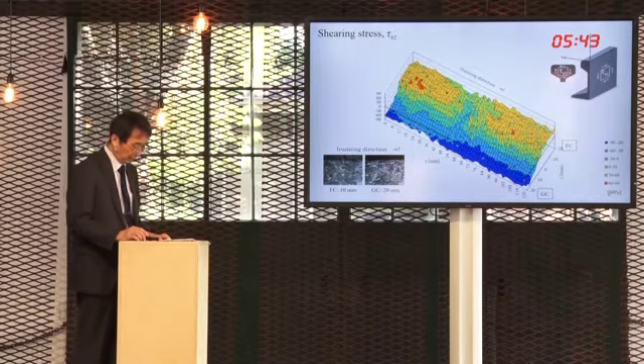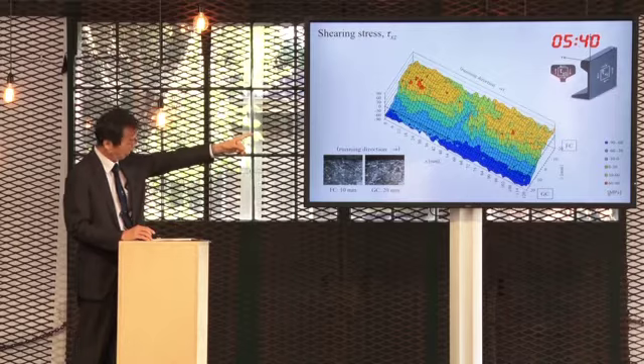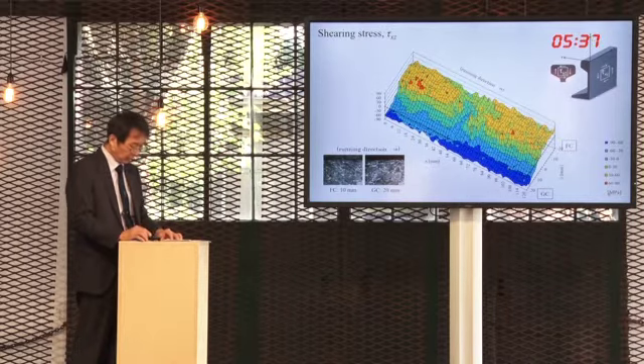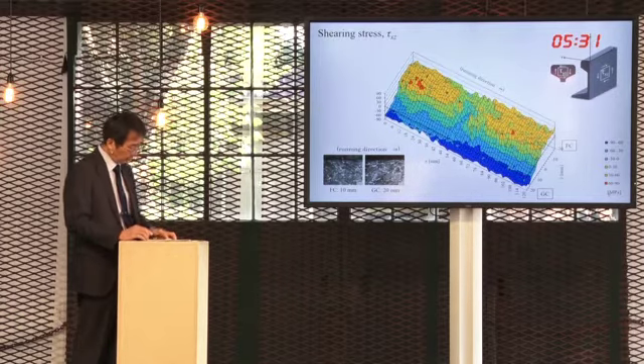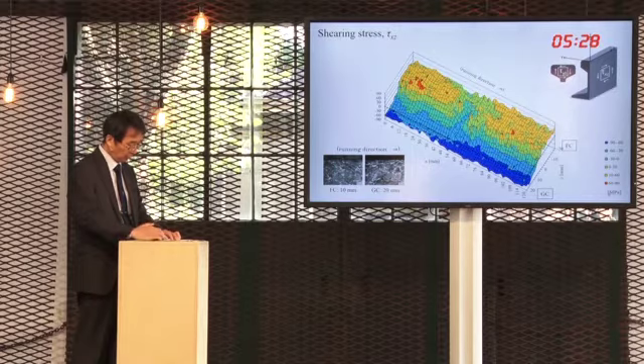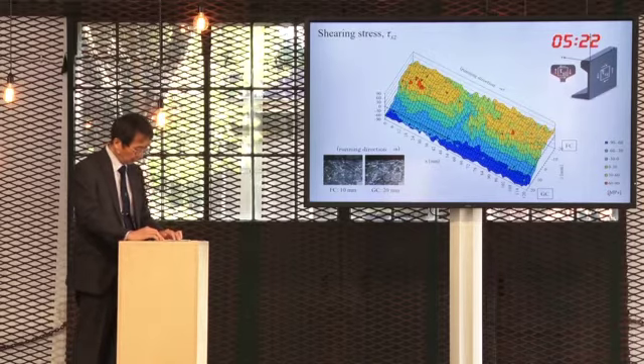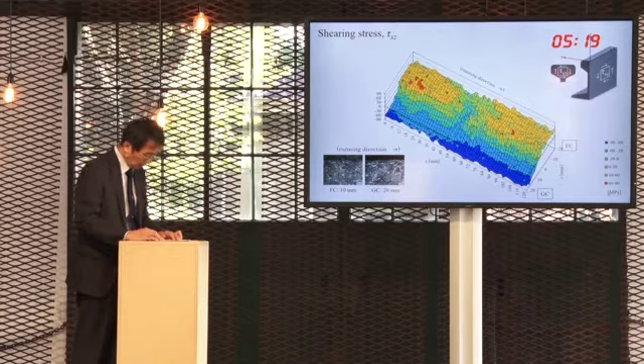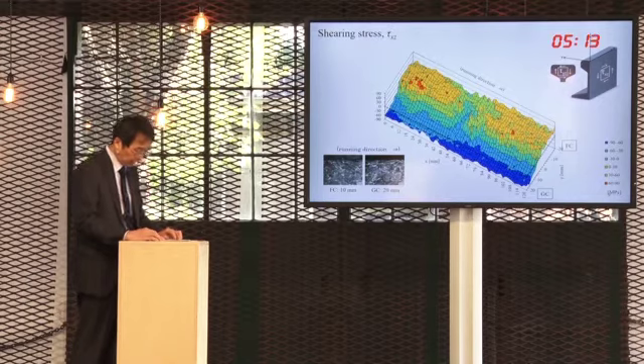The result of the stress calculation is shown in the slide. Shearing stress tau xz is plotted here. Tau xz acts as shown in the upper right figure. We can see that there are 2 features in the mapping of tau xz. One is the relaxation of stress around the center of the rail. As a crack formed near the center, it's thought that the restraint in the surroundings of this area disappears due to crack initiation, which made the stress relax.